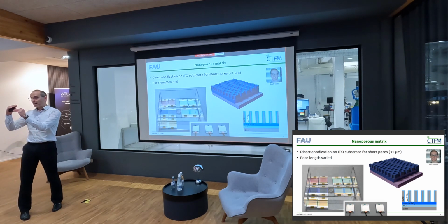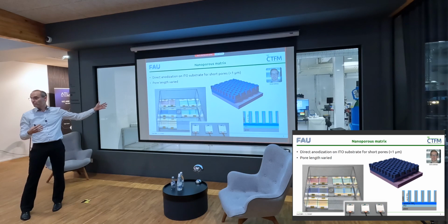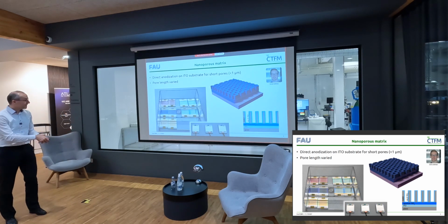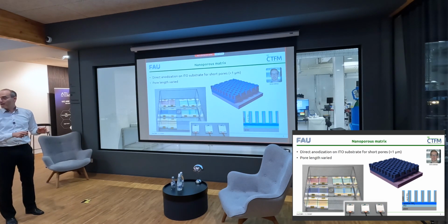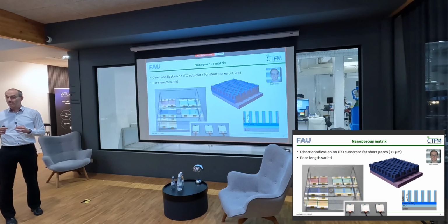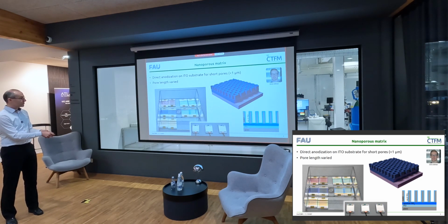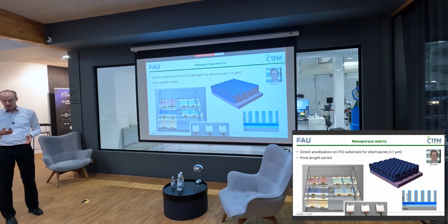And if the length of the pores, that's the thickness of the porous layer, is on the order of some microns or even submicron, then you get colors due to interference. And the fact that the color on each sample is very homogeneous from left to right means that the geometry is very well controlled. Here you have 5 pairs of nominally identical samples made on 2 different days, and you see also the level of reproducibility that we get.